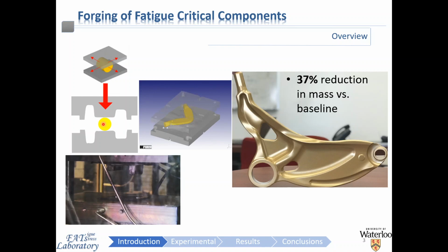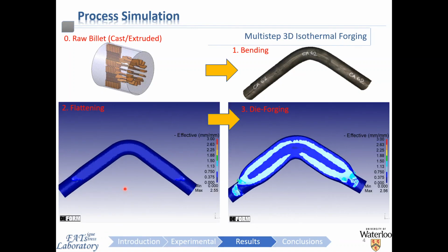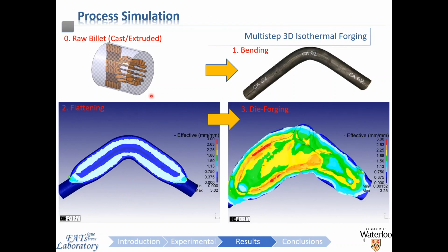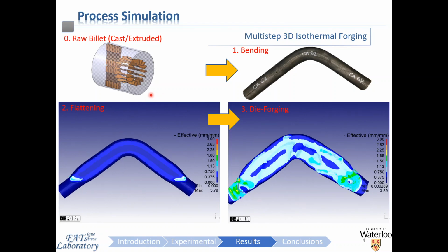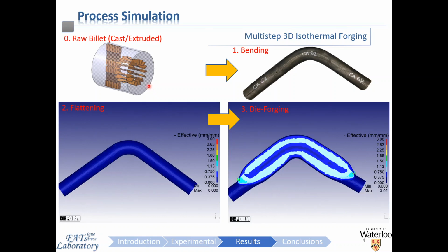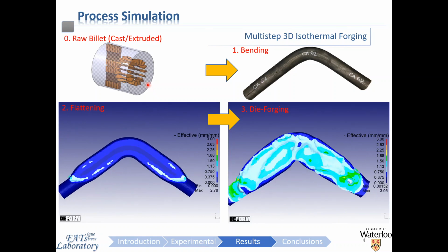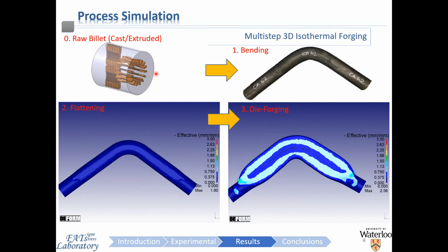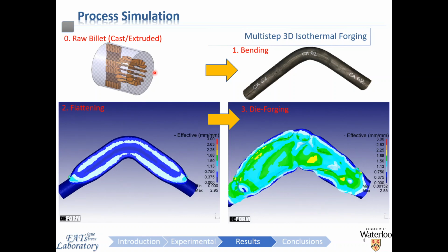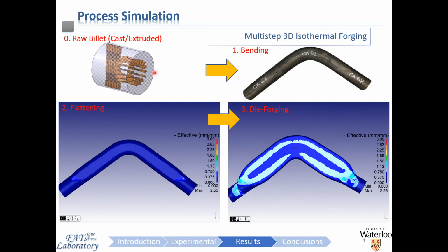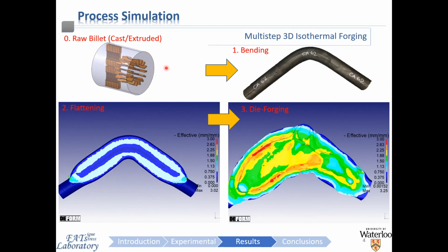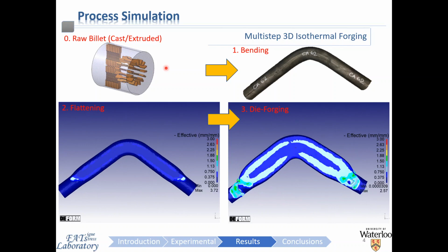This can have many beneficial effects for fatigue and some detrimental ones if the process is not carefully controlled, as is done generally at a moderate temperature between 250 degrees Celsius and 450 degrees Celsius. As the component which was selected for this particular investigation had a quite complex geometry, we quickly figured out that we needed a multiple step technique to fully optimize each parameter of the forging process. However, this is a costly undertaking, as die tooling, heating energy requirements, and physical complexity often make the adopted process a compromise of a pragmatic requirement and scientific ideals.